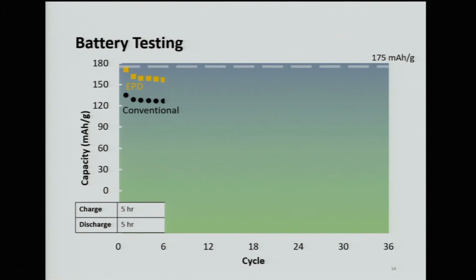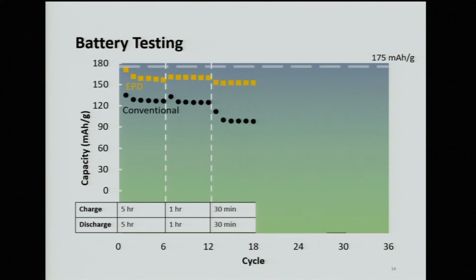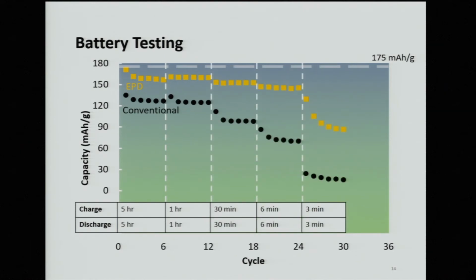So let's make it faster. Let's take 1 hour to charge and 1 hour to discharge. We see no difference. So let's speed it up even more. 30 minutes, 6 minutes, 3 minutes. Now we're really seeing a difference between the EPD and the conventional electrode. At 3 minutes, the conventional electrode capacity doesn't reach half of what the EPD does. So we can say that the EPD electrode performs better in fast rates.